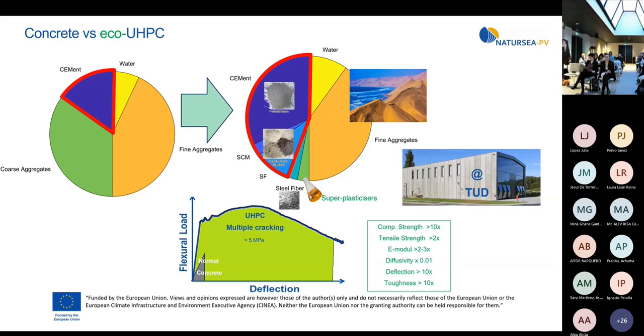But the diffusivity is actually governing how much chlorides diffuse through this concrete cover, because when they reach the reinforcement steel, the corrosion starts. So this is the main focus. We focus on the chloride ingress, and I think I will explain it in the next slide.